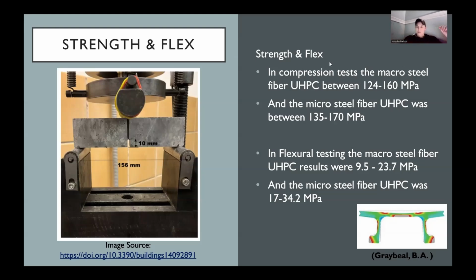The test results from one of my many sources tested the difference between macro and micro steel fibers, and the results are on this page. First, the strength, the compression test. It withstood 124 to 160 megapascals with the macro steel, that would be the twisted and the waved version. And the micro steel fiber ultra high performance concrete was able to withstand 135 to 170 megapascals before failure.